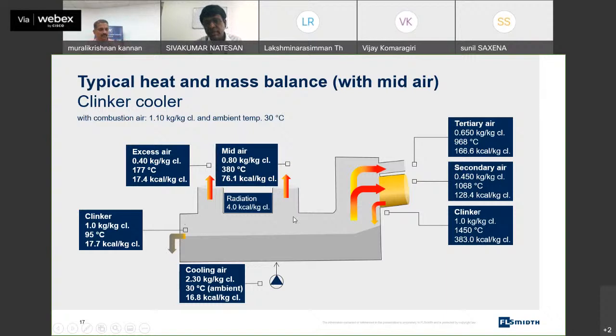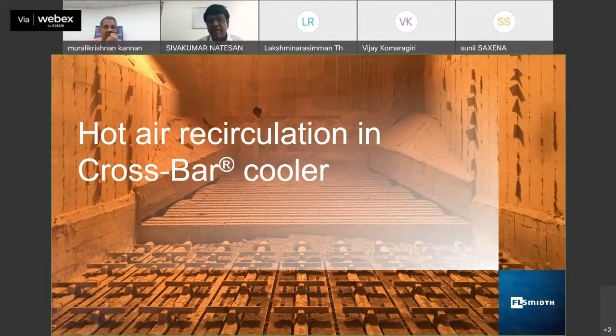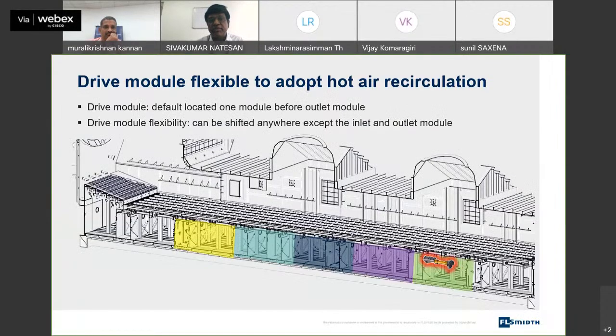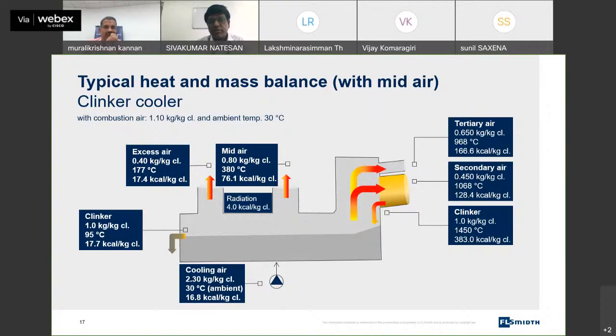This helps us in getting the high quality heat transfer to the mid-air and WHR potential and all those things. You can see that we can take up to 0.8 kg and 380 degrees as a mid-air temperature. The lower the mid-air quantity, the temperature can be even higher. But the parameter that can be compared is how much cooling air you are inputting to get the same benefit. If the cooling air flow is less, it means that the cooler is much more efficient, because it's using less airflow for the same cooling effect. And even the airflow we have seen here can be recycled back to the cooling air to get the benefit of extra heat transfer.